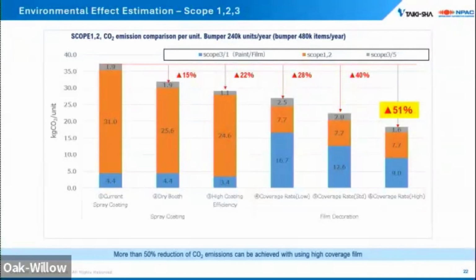But the film process is more significantly affected by a high coverage ratio than a traditional spray application is to a high TE application. As Iwakoshi-san mentioned earlier, that coverage ratio really is key in terms of your efficiency of material usage. And when you consider a high coverage ratio, your benefit, even including the Scope 3 emissions of the film manufacturing and waste, is greater than 50%.